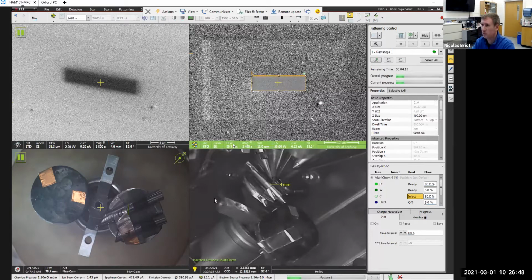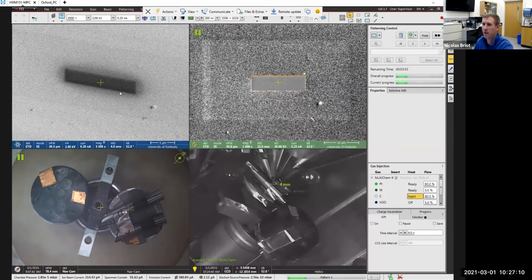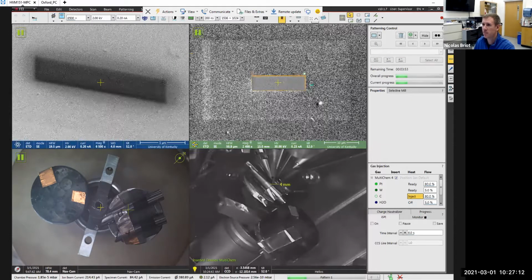So again, the tube is flowing a precursor gas that adsorbs at the surface of the sample, and we use the energy of the beam, whether it's the electron beam or the ion beam, to decompose that gas into a volatile part that's being pumped through the system, and it leaves some solid residue that is what we're trying to deposit. See how the pad is growing nicely here, and then we cut through it perpendicular.